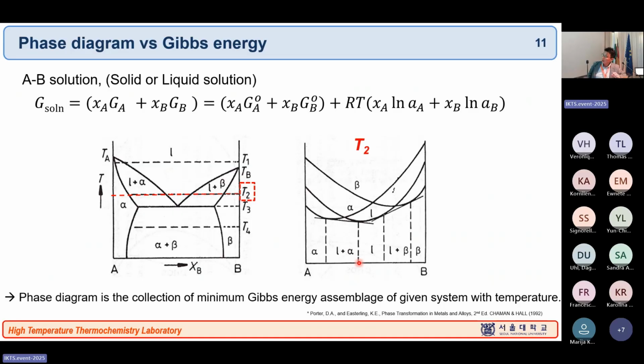Okay, now, when you know the Gibbs energy function for the solution phase, so for example, solution AB, their Gibbs energy is simply the mechanical mixing of the partial Gibbs energy terms, then you can rearrange this one as a standard Gibbs energy with that extra term, that's the activity term. Okay, so if I know the activity change depending on temperature and the composition, then I can draw the Gibbs energy in any composition, any temperature domain. Okay, then, for example, let's look at this one, at T2 temperature.